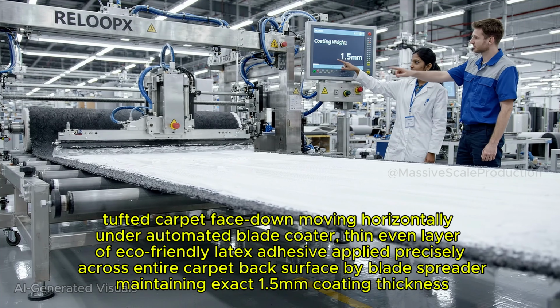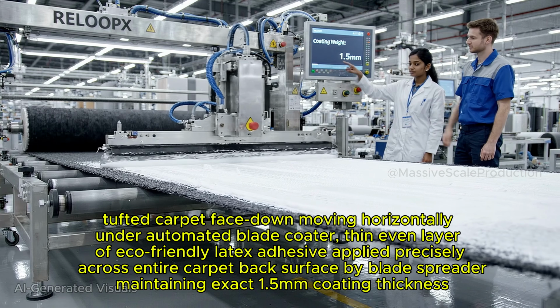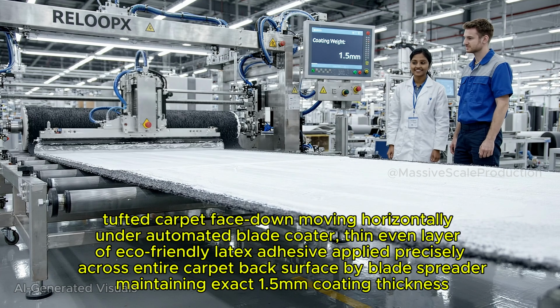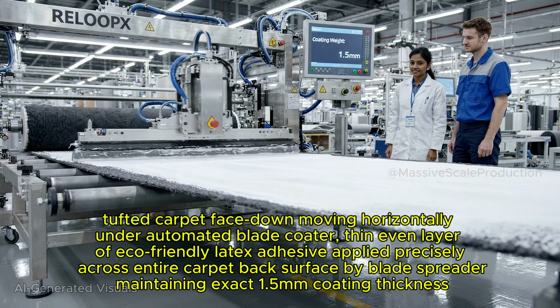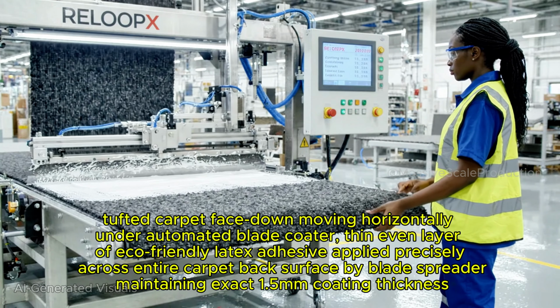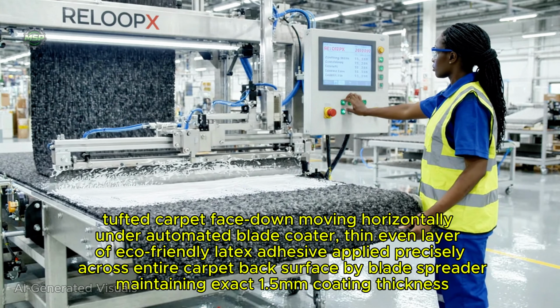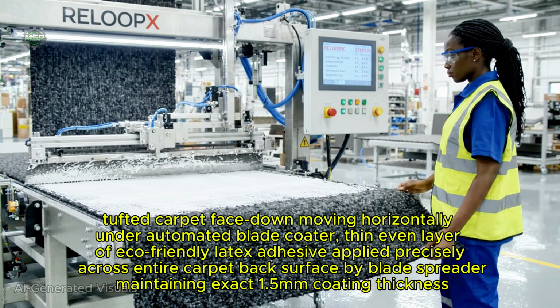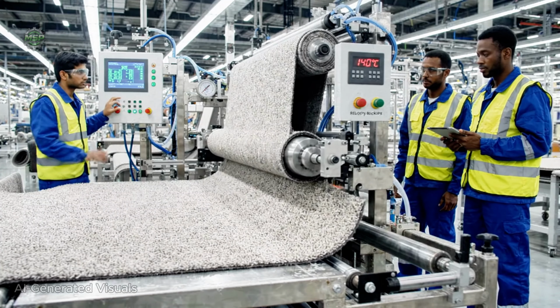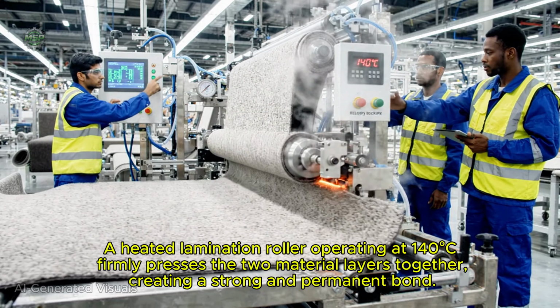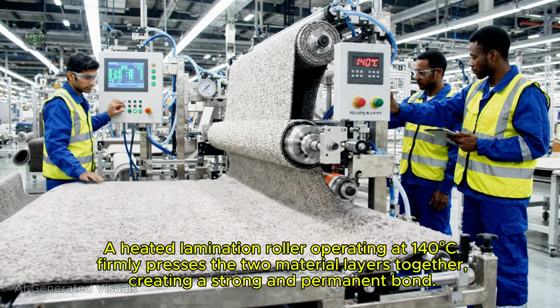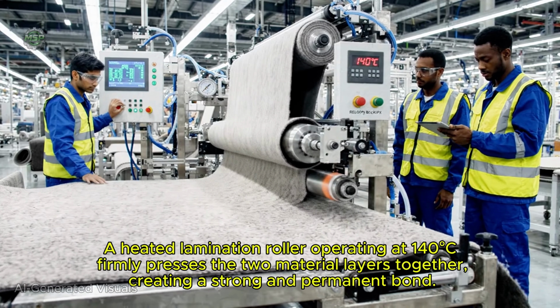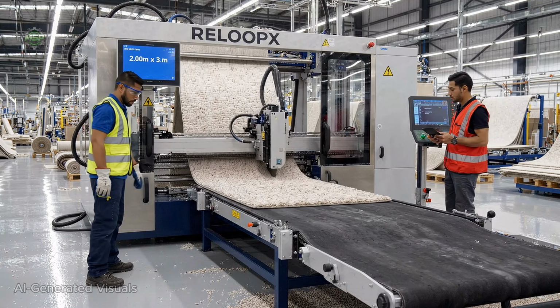Tufted carpet face down, moving horizontally under an automated blade coater. A thin, even layer of eco-friendly latex adhesive is applied precisely across the entire carpet back surface by a blade spreader, maintaining an exact 1.5 mm coating thickness. A heated lamination roller operating at 140 degrees firmly presses the two material layers together, creating a strong and permanent bond.